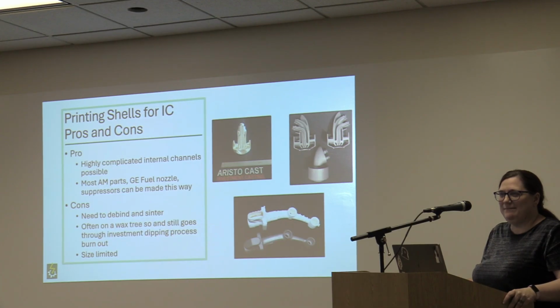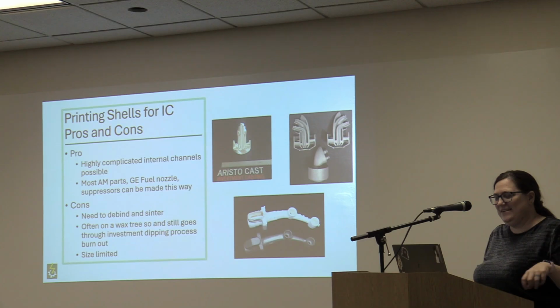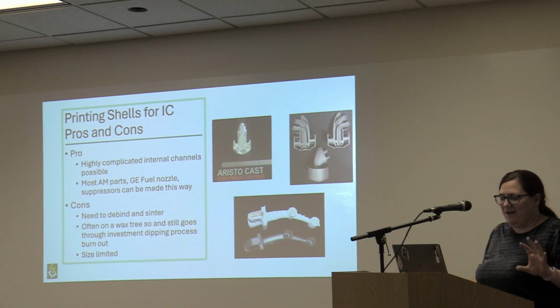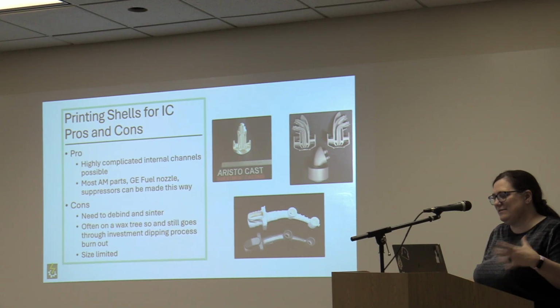Drawbacks, you still have to debind and basically get rid of that polymer part of the resin, and then you have to sinter the shell. They often will still assemble this on a wax tree, so it's still going through this very long process, which is why these still tend to take several weeks of process time.